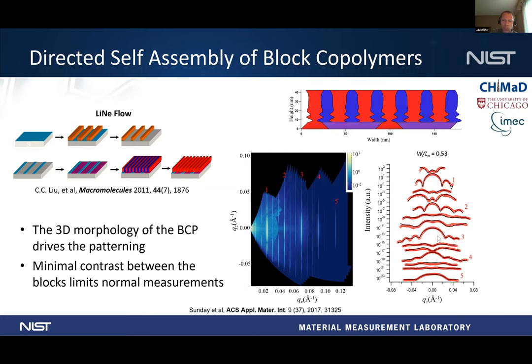And so this is just showing vertical line cuts through that data and then showing the fits to that data. And so this is a structure that was fit to it. The waviness at the bottom, I don't think that's the way the structure really is. There's actually fluctuations in the material along there. Since we're measuring the average structure, when you have something that's not the same the whole way through from those fluctuations, that can sometimes give rise to a little bit of a strange pattern there.